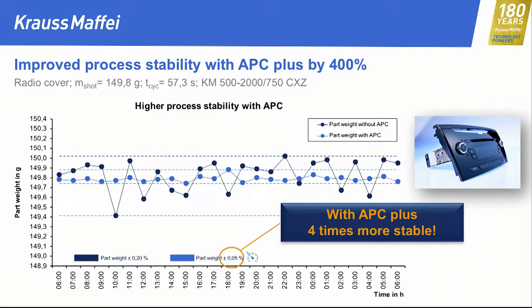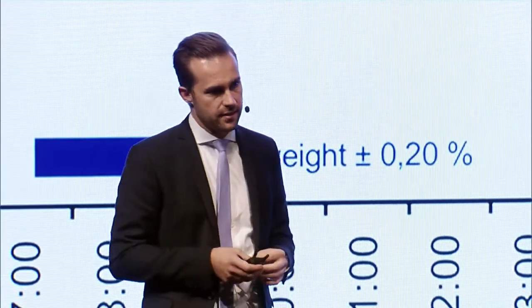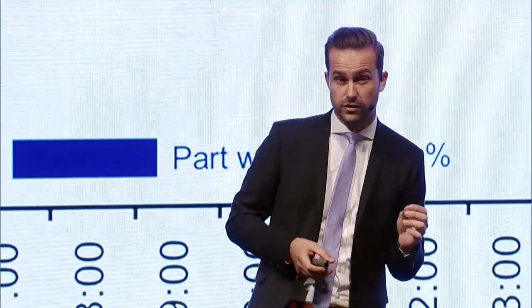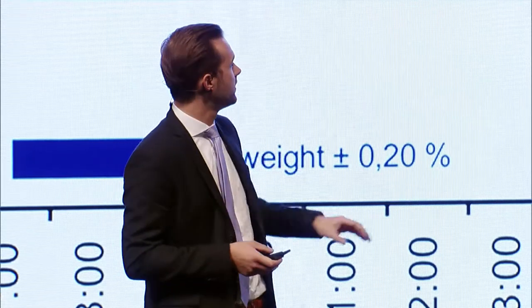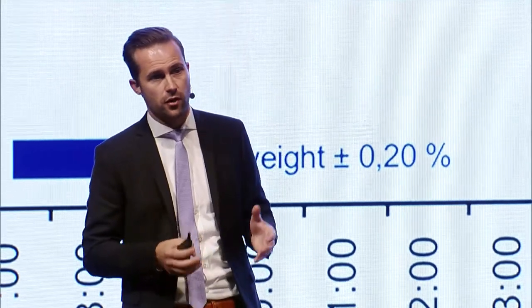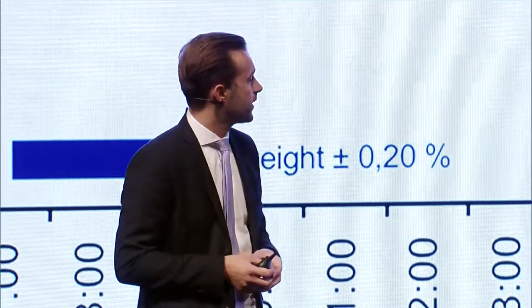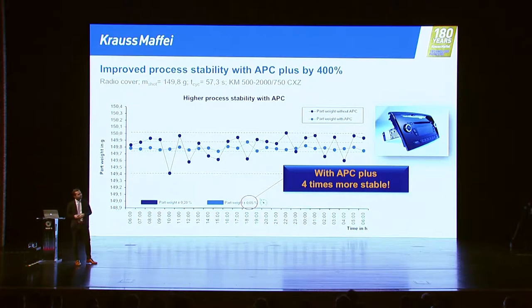I brought you one result that you can see here. If you do not activate our APC plus function, that's the dark blue line. The shot weight is slightly in a specific range. We have a part weight of plus minus 0.2% in this example. If you activate APC plus and you take account of these changes in viscosity, we are able to have a process which is 400%, so four times more stable compared to without the APC plus function.